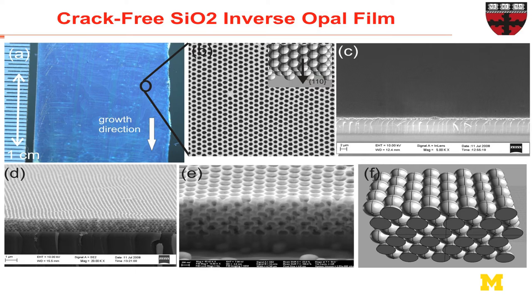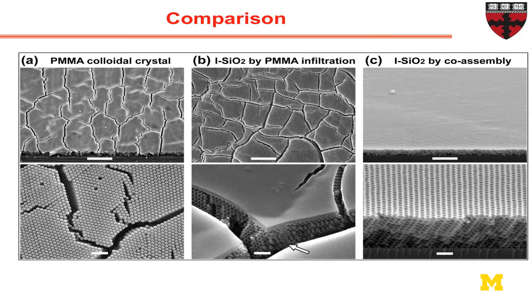if gelation takes the same time as colloidal assembly, will provide a gluing to your system to make films at a huge length scale, whatever size you want, that would have pretty much no cracks in them on a very large scale. That's nice, and obviously it's much better than direct colloidal crystal, it's better than colloidal crystal that was then infiltrated and converted into inverse structure, because there's a lot of overlayer formation, cracking due to infiltration and the stress related to that.